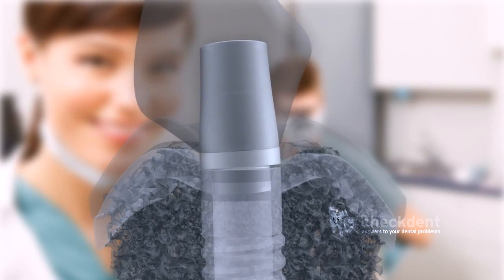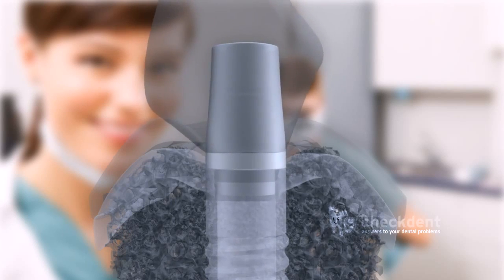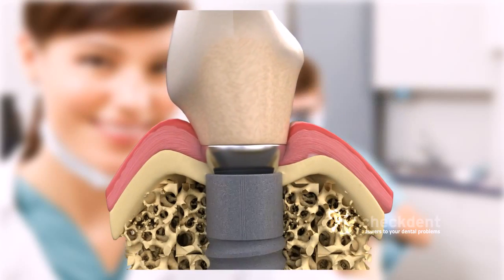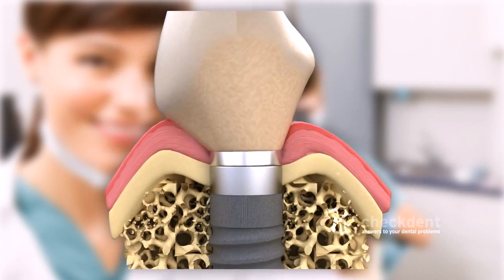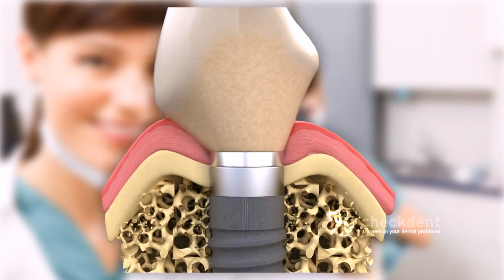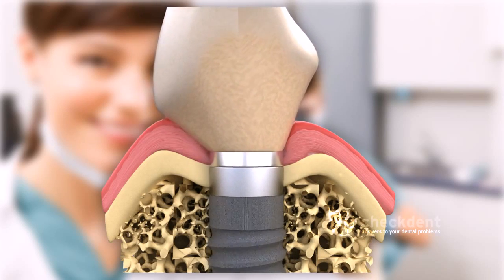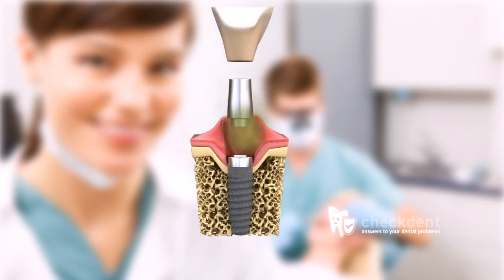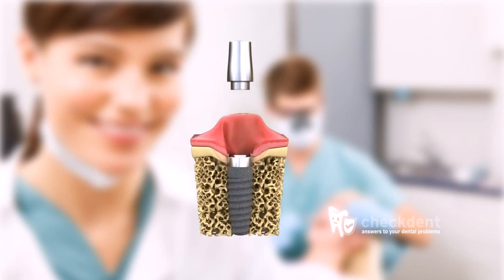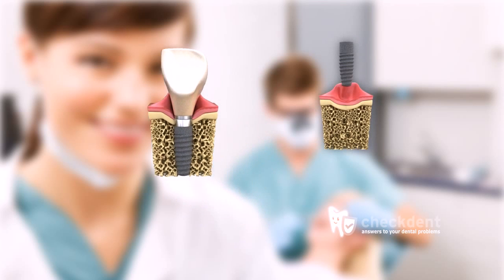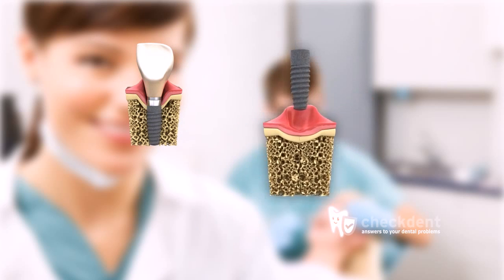Because of this pumping effect, bacteria are transported outside and around the implant, leading to the foul smell and the initial loss of bone. In contrast, there is absolutely no movement with conical connections. The results of conventional plug-in connections are a bacterial invasion of the microscopic gap — chewing forces pump the bacterial soup out of the gap, leading to plate-shaped bone defects and the foul smell. By polishing the upper part of the implants with plug-in connections, the spread of bacteria can be interrupted, but the body will still have to fight the bacterial soup that exists there. All this is avoided with conical connections.